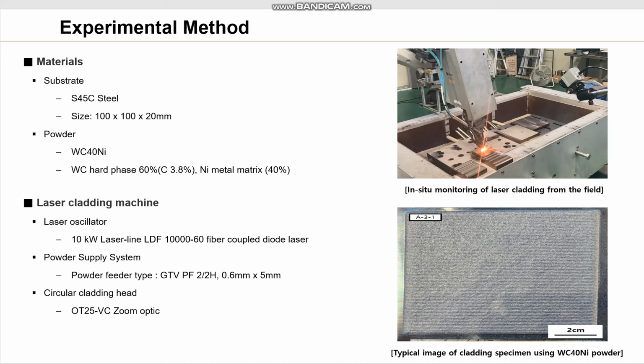Okay, this figure at the right top of this slide shows the real-time monitoring system for laser cladding. The thermal imaging camera was located within 1 meter of the base material in a straight line and was set so that the area of interest was not obscured by the laser arm during the laser cladding process. Okay, the laser cladding works were performed after preheating the specimen to 300 Celsius degrees to reduce the incidence of pores and cracks caused by the temperature difference between the base material and the laser. The direction of laser cladding movement was from left to right, and the entire surface of the specimen was coated starting from the upper left corner of the specimen.